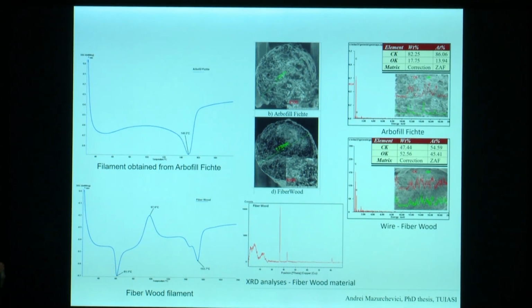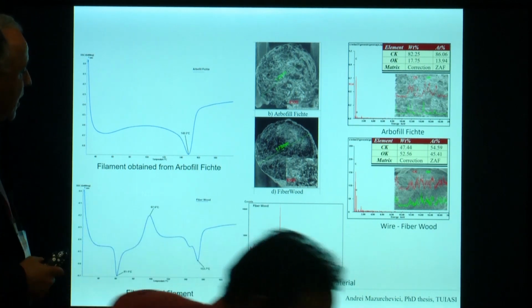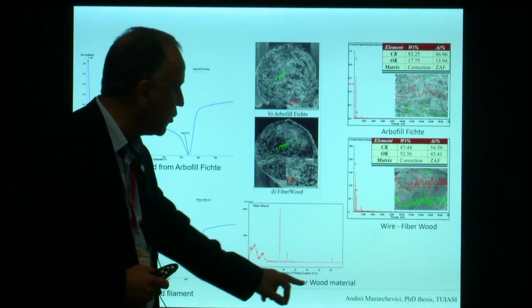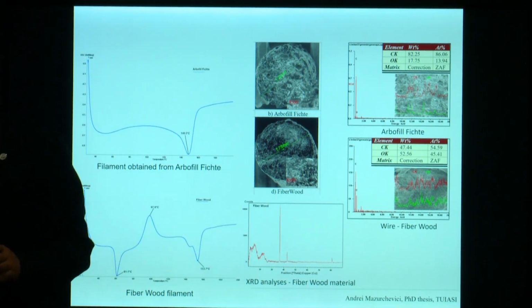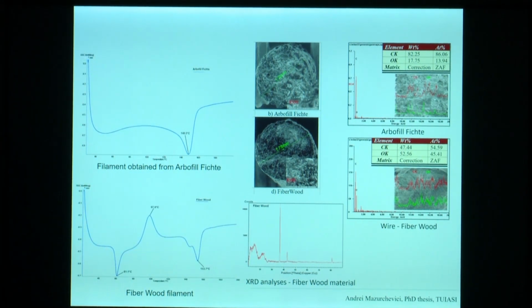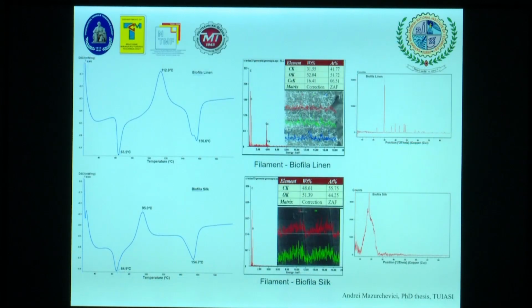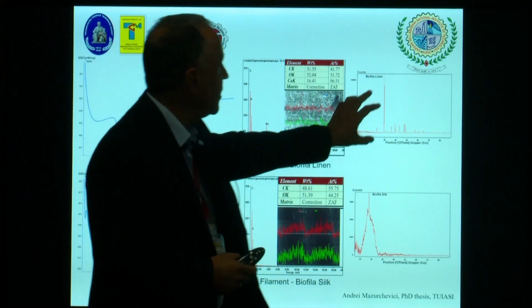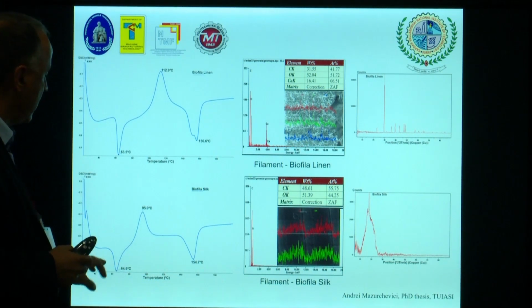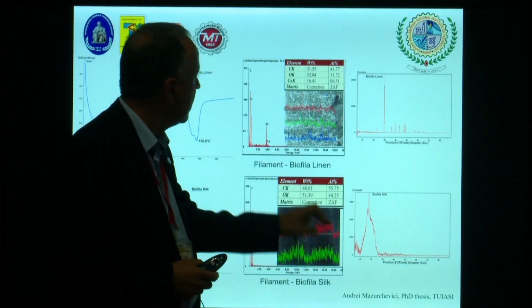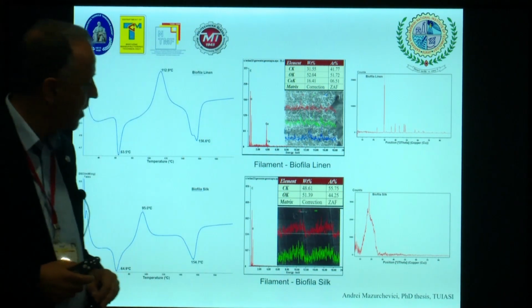Fiberwood, also you can see the same glass transition temperature, and XRD analysis for fiberwood material also confirms that the material has an amorphous structure. And also on the right side, carbon and oxygen are the main elements of the material, so again it means the biodegradation rate. You can see also the Biofila linen with amorphous structure, Biofila silk, again carbon, oxygen, and also the amorphous structure.